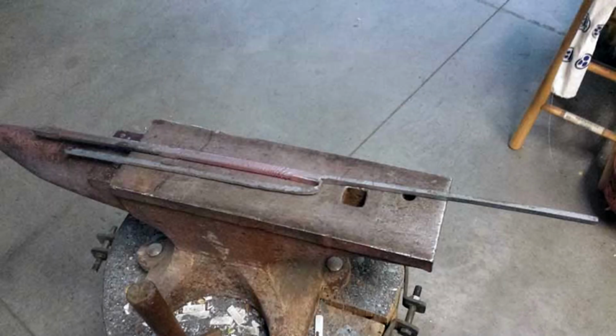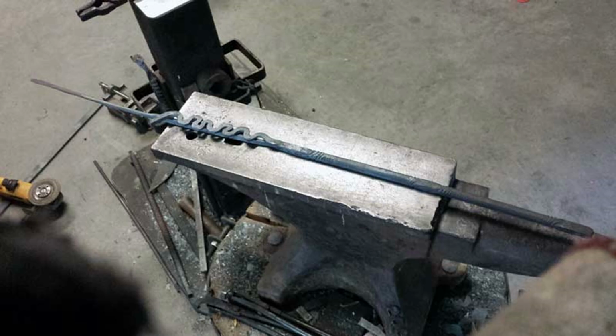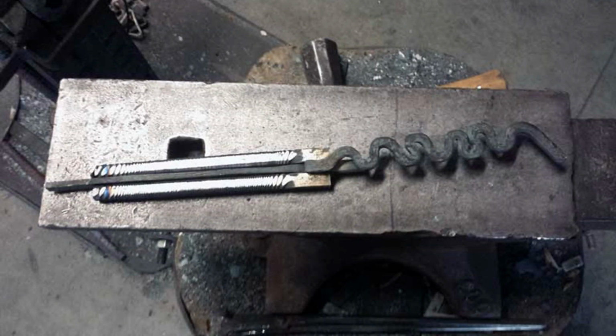This is my first test to work out the details to create the serpent as an inlay, using the central bar of the 3-bar pattern and splitting it in half. One half remains as part of the 3-bar pattern underneath, and the lifted up half becomes the serpent. I had done the waves by hand, which resulted in an irregular pattern as in the original blade. The bottom half of the split is sandwiched between the two twisted rods to form the 3-bar pattern.